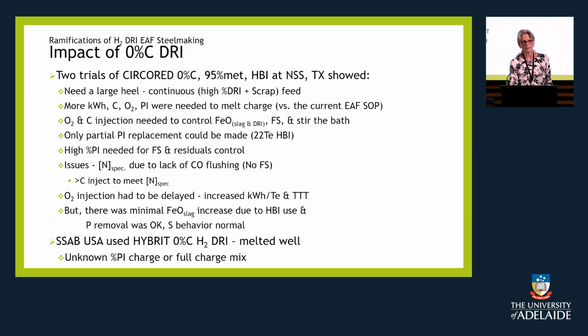They had issues in making the low nitrogen requirement from the plant. That was due to the lack of flushing from the CO that wasn't being created. They had to delay the oxygen injection to make sure that they could keep the furnace operating properly. SSAB has actually melted some of the hybrid zero carbon material that they produced in Europe. They melted it in the US of A, and they found no problem, but we don't know how much pig iron they were charging at the same time.